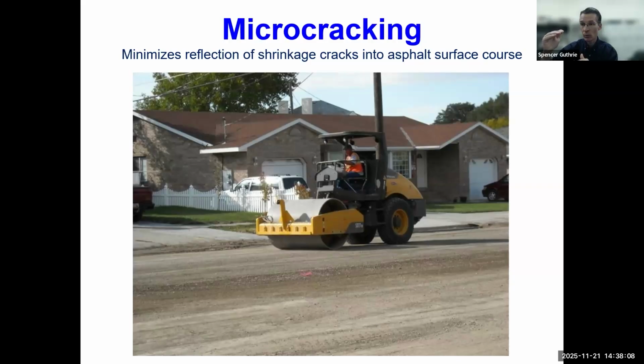And if they thickened it to the proper depth, they were going to have to put in guardrail along a long distance of the interstate because there was a drop off. It was right on the level of being okay, but any thicker would produce a deeper drop off and they'd have to put in a guardrail. So they decided it would be cheaper to just remove a portion of the cement treated base and avoid putting in the guardrail. They succeeded in doing it, but they did have to replace some extra teeth on the reclaimer. Okay, is that okay for that question?